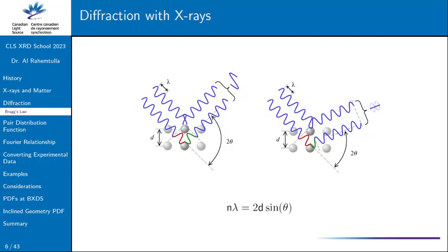So now that we have that principle for that atom, if we imagine a crystal, it's going to be a whole mess of atoms arranged in this very periodic, repeating way. And we've already seen a bit of Bragg's law, but if those atoms start forming these nice, very infinite planes, we have cases where photons can come in and scatter off of these planes. And if these planes are spaced in the right way, we can get constructive or destructive interference, which starts giving us information in Bragg scattering that we can use in powder cases as a fingerprint for solving structures.